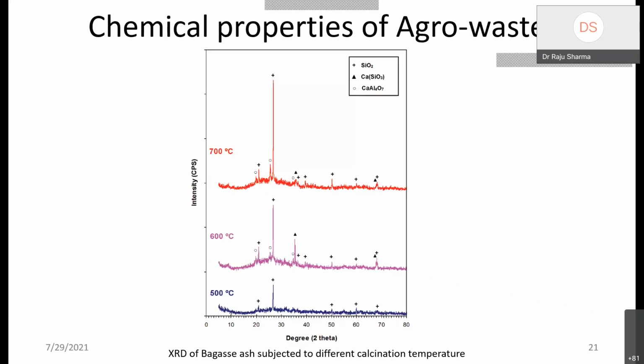So if you see here, around 27 degrees 2 theta, you can see a peak with a plus sign which shows SiO2, right? So here you can see the amorphous SiO2 increases as the temperature is increased. And you can also see at 500 degrees Celsius there is almost no CaSiO3, but when you increase the temperature, you get the peaks of CaSiO3, right? By this way, you can analyze how the calcination, how your treatment of the waste, improves the final property of the concrete.